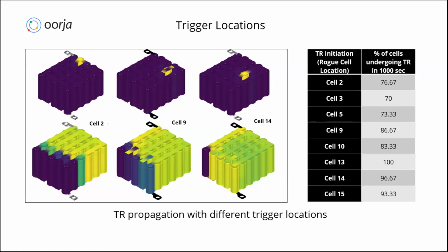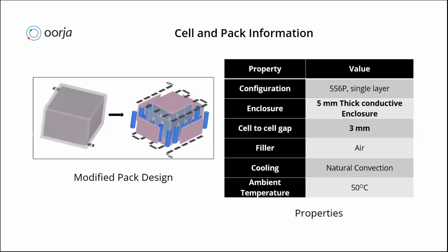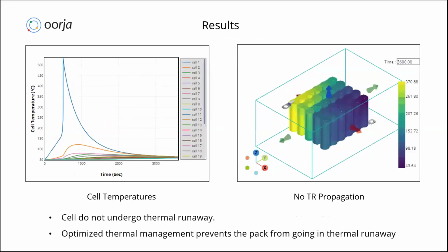So this is the kind of what-if analysis you can easily perform using Oorja, considering the defective cell location and, based upon that, how the thermal runaway propagation happens, and then make the design modifications in order to prevent that from happening, like we have done here in this TR mitigation study. So what we did was we used the same pack, but in this case, rather than a pack without casing, we included a 5 mm thick conductive enclosure. And because of that, you can see that even though a defective cell undergoes thermal runaway, the rest of the pack is saved. The rest of the pack doesn't undergo thermal runaway in that case.